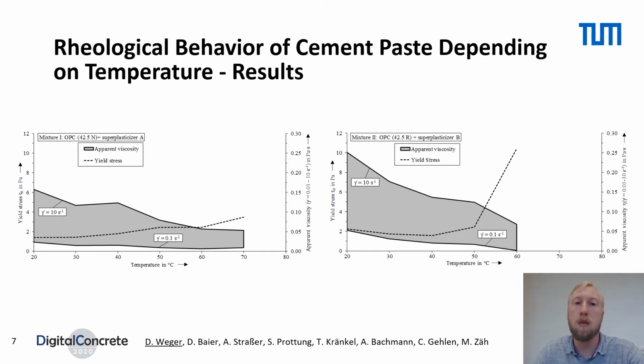Looking at the measurements of the apparent viscosity, the results exhibit a decrease of the apparent viscosity for both mixtures between 20 degrees Celsius and 70 degrees Celsius. Experiments showed that a low apparent viscosity is beneficial for the penetration ability of the cement paste in the particle bed. One possible explanation for this, besides others, is the increasing absorption behavior of the superplasticizers with increasing temperature.